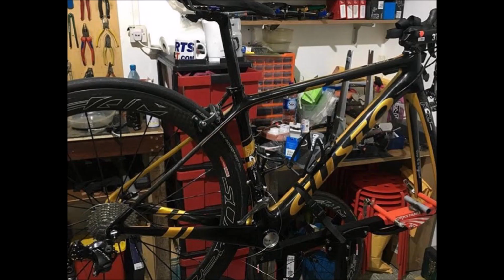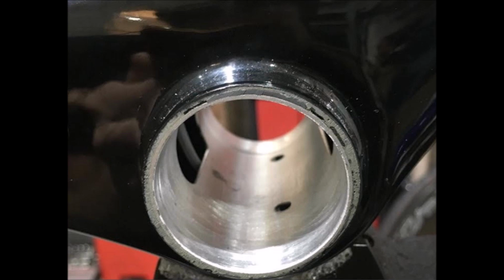And then the owner switched to this one, which is a Chinese brand bike called Gusto. Gusto is the Italian word for flavor, but there's nothing Italian about this bike. It's also the same system, as you can see from this picture, a bonded-in aluminium sleeve into a carbon fiber shell. You can also see this one's been very badly made. You can see the gaps around the sleeve where the glue is missing. You can also see that it's quite uneven. And you can see how easily water is going to be able to get between the aluminium sleeve and the carbon fiber frame through all the holes that have been put in for the internal cable routing.